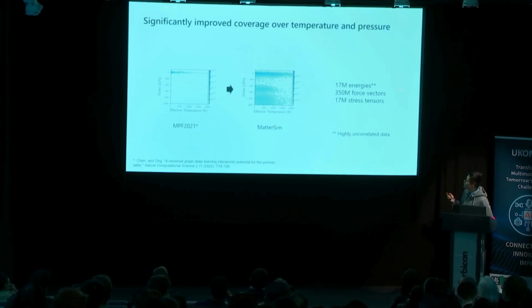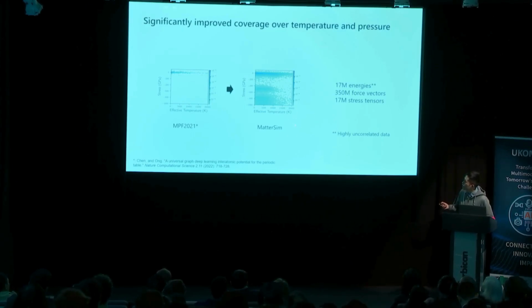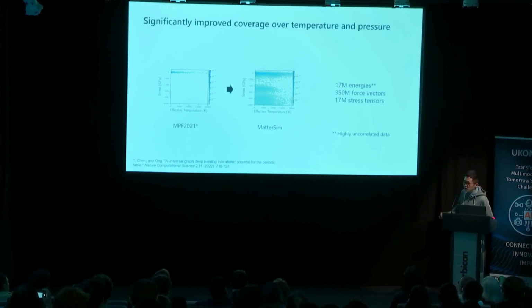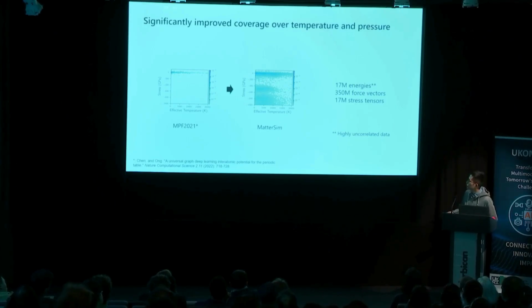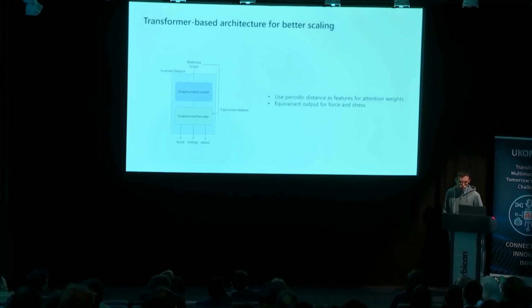What it leads to is a data set that incorporates around 17 million structure energies and a lot more forces. You can see the plot of all the data points in the energy and the stress, which corresponds to pressure space. You can see that it covers a much bigger space compared with the previously well-known data set called MPF 2021. One key aspect of this data is that it's also highly uncorrelated, because we use this uncertainty quantifier, so every single data point is different. There are some bigger data sets out there in the community, but this data set is one of the most diverse compared with the ones already available in the public domain. We also developed a transformer-based architecture to really fully consume these data sets.